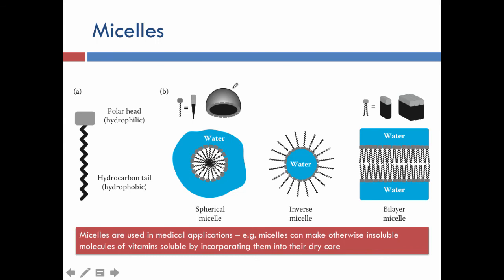Well, as I hope you can expect, the polar groups of those molecules are going to be attracted to one another, and the tails are going to be attracted to each other. And so that's going to mean that they're going to spontaneously self-assemble into several structures, and these are just a few. The term micelle is the term that we're going to use for these kinds of spheres or balls, or perhaps you can think of them as molecular droplets, because the water is either going to be on the inside of this micelle or it's going to be on the outside.